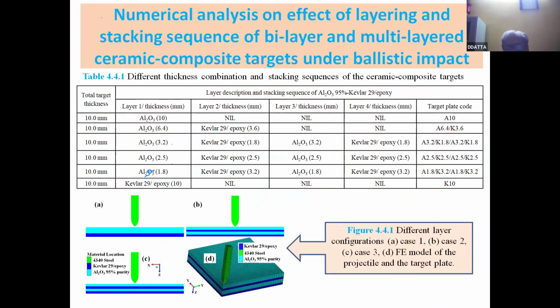Layering and stacking sequence is another aspect. I just tell you the crux of this simulation, that we tried to see that suppose we are going for a 10 millimeter plate or 10 millimeter armor. So out of which, how much thickness we will give to ceramic and how much thickness we give to composite? Is it 50%, 50%, 5 millimeter, 5 millimeter, or more for composite, less for ceramic, or more for ceramic, less for composite?